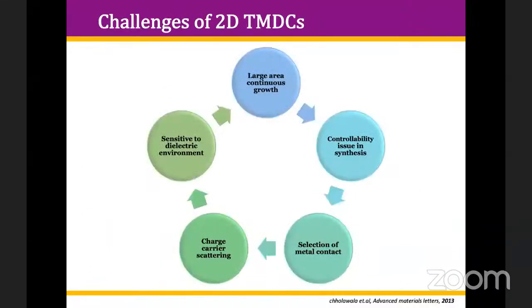What are the challenges for two-dimensional transition metal dichalcogenides? The challenges are that these materials are very difficult to grow over a large area, because they are obtained just by exfoliation. You can remove the material, but when you are removing it, the removal of continuous material is very difficult. So large-area continuous growth is a big challenge. Then controllability or homogeneity in the growth is a critical issue.